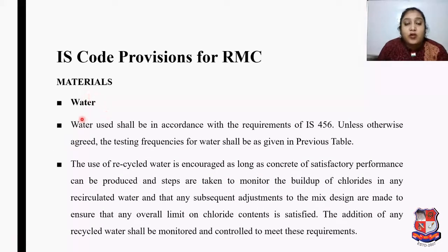If we talk about the water, then water used shall be in accordance with the requirement of Indian Standard 456 unless otherwise agreed. The testing frequencies for water shall be as given in the previous table. The use of recycled water is encouraged as long as concrete of satisfactory performance can be produced and steps are